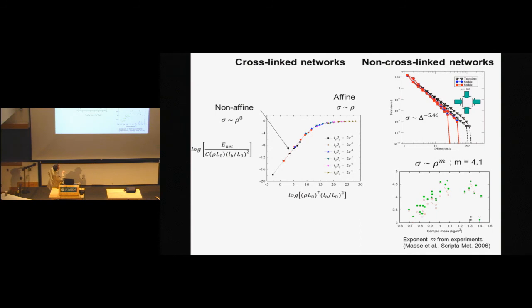Okay? Now, here is how the non-bonded network responds to compression in this case. So I'm taking a box filled with fibers, non-bonded fibers, and I compress it, okay? And I plot stress versus strain, in particular pressure versus dilatation strain. And what you see is a very beautiful and long-range power law, which extends essentially over the whole range of loads from percolation, which means from the point when these fibers actually make contact with each other and start pushing back at you, to full compaction, which is this last point on the left. Okay, so very beautiful power law.